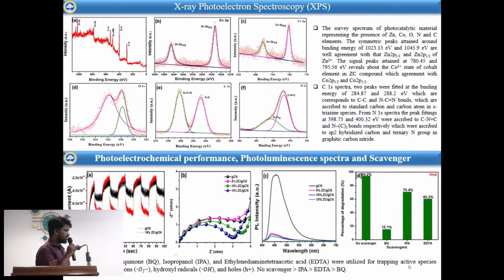And we have also calculated the scavenger analysis. So scavenger analysis is generally to note which radical is participating most in the reaction process. So we have taken benzoquinone, IPA solution, as well as EDTA. Each one has a role: benzoquinone for superoxide retardation, isopropanol for hydroxyl retardation, and EDTA for hole retardation.